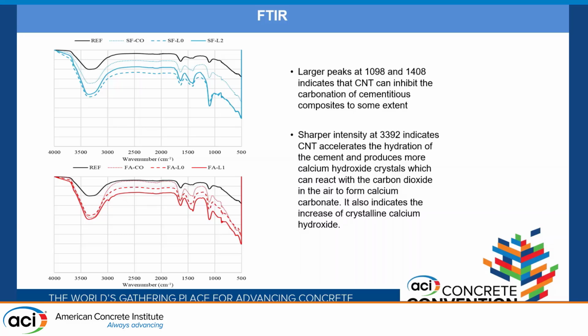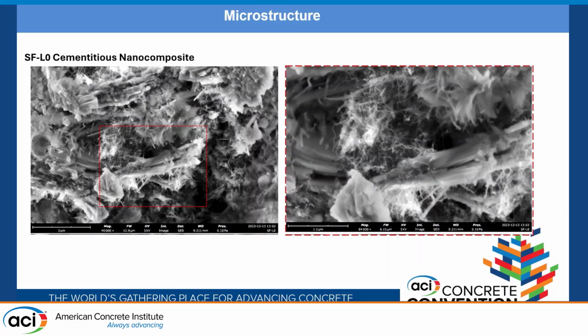There is a lot of early research that has been done in this area. With all the mixtures that we use here, it is the same amount of CNT that we mixed in. By having a more pronounced effect of the hydration acceleration and also the inhibition of carbonation, we're trying to see if the process that we have helps the dispersion, which the FTIR spectrum is showing that trend, and with the latex polymer emulsification process that essentially pushed towards where we wanted, a more pronounced effect.